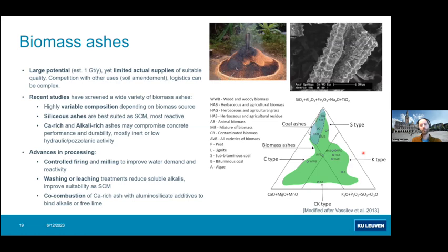One important point is that firing should be controlled and probably optimized to obtain an ash composition or ash crystallinity which is optimal for reactivity. So firing and milling, so processing, is very important to improve water demand. Water demand is typically quite high for these materials. If there are issues with soluble alkali, washing or a leaching treatment can help.